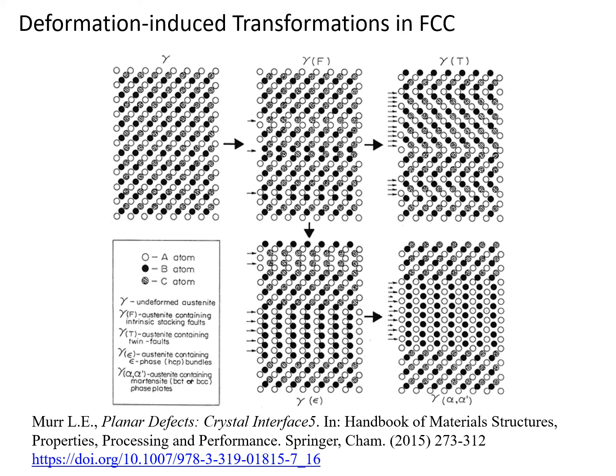If you apply that shear, rather than just on one individual plane, which would create a stacking fault, but in a bulk, we apply it over numerous planes successively, the same shear, all in the same direction, we end up with this arrangement here, which is a twin. If we sheared alternate planes, not successive planes as we have in the twin, then you change the crystal structure from gamma FCC to epsilon, which is HCP.